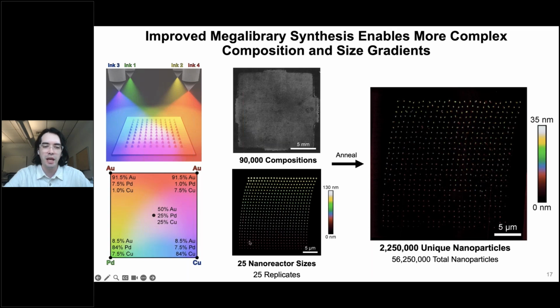And then if you look at a pattern created by one of those pen tips, we can now introduce size control in this patterning. So now each row is patterned at a slightly faster speed. And as you pattern faster, the tip is in contact for a shorter period of time. And so you get these smaller nanoreactors. And then as you heat it up, each of those nanoreactors is converted into a nanoparticle. And so now you can see the larger, about 35 nanometer particles at the top, and smaller, roughly 15 nanometer particles down at the bottom. And so in total now, with 25 sizes and 90,000 compositions, we have over 2 million unique nanoparticles. And then each one has 25 replicates, so you have over 56 million in total.